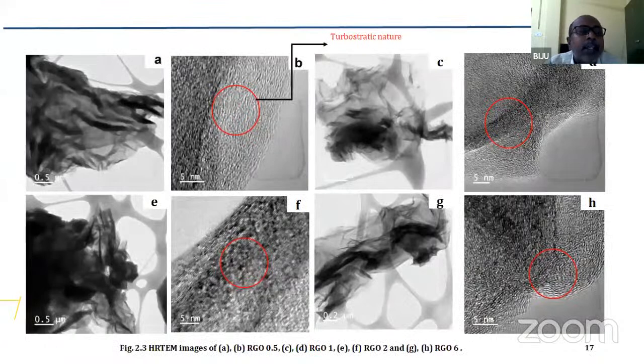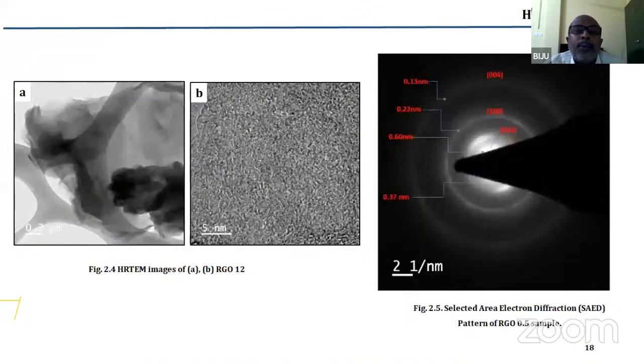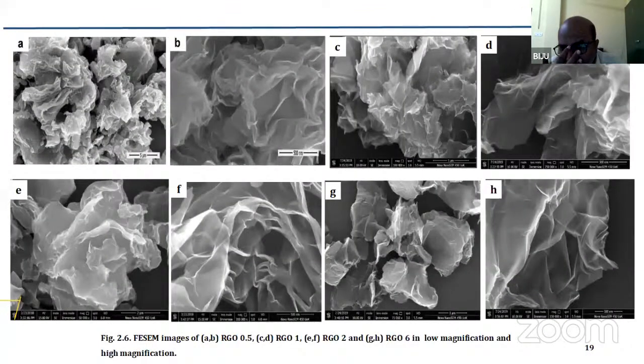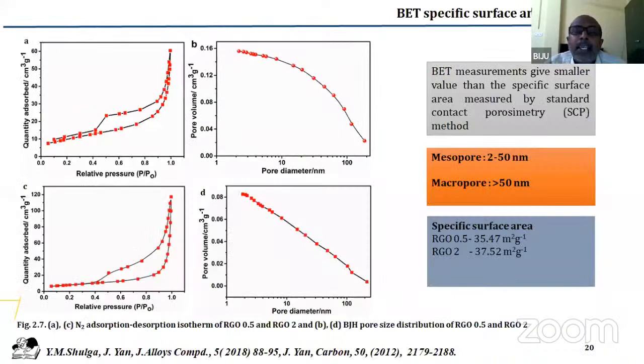And we also did the transmission electron microscopy studies. The high resolution transmission electron microscopy studies also supported the XRD results that it is turbostratic in nature. Now, the SEM analysis also was done, which again showed the layered structure of RGO. Specific surface area measurements were also done. The specific surface area of the samples was in the range of 35.47 meters squared per gram for RGO 0.5. These values were not very high nor very low.